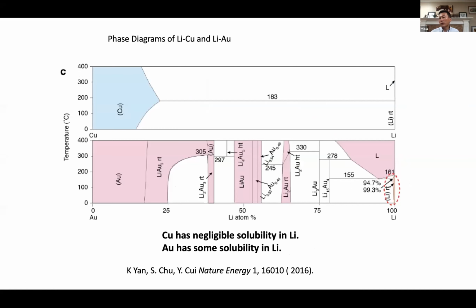This turned out to be related to the phase diagram. For the case of copper, on the pure lithium metal side, copper has no solubility in pure lithium, but gold has some solubility. What that means is the lithium coming in has the ability to dissolve gold away, but not copper. That's why copper can be used as a current collector.